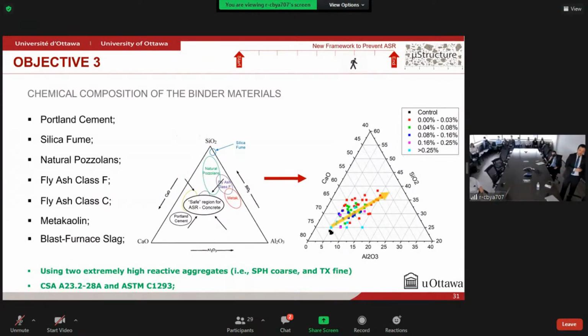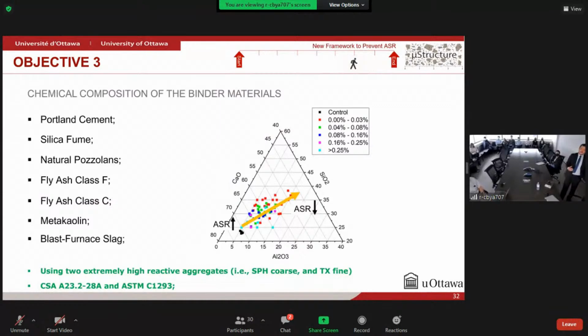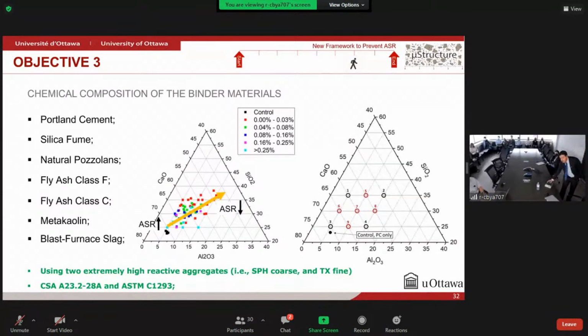For that, we went back through the literature. We plot the results from the literature in this graph here, and we can see that following this yellow arrow here, we have a trend to prevent better the development of ASR in concrete. So with that information, we then select 9 different points in this plot to first try to map the behavior of this path of prevention against ASR, and then to understand better the influence of the main oxides in the prevention against ASR. Also, I would like to mention that it's such a great thing to have these points fixed because we can analyze them differently.